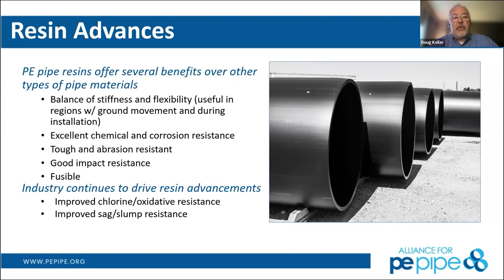One of them being improved chlorine or oxidative resistance. So chlorine disinfectants are typically used in water systems, in the secondary water system in the distribution, to keep the water clean until it gets to your tap. We've been able to deal with and address the issues that earlier generation polyethylenes had with oxidative resistance. And what we're going to talk about today is the improved sag or slump resistance. This allows us to make larger and larger diameter polyethylene pipe than we could make in the past. So that 48-inch and greater that we're talking about today is because of the low sag materials.